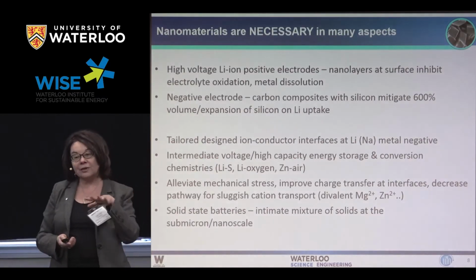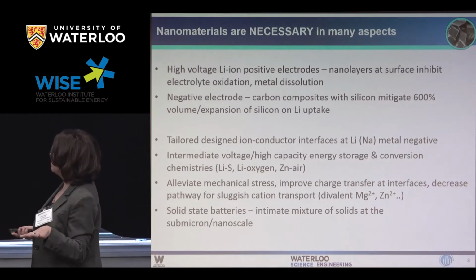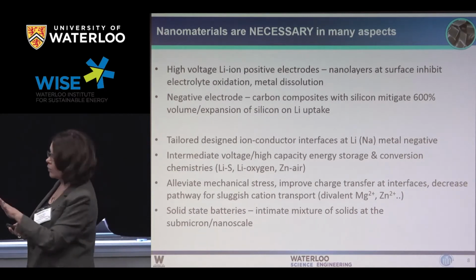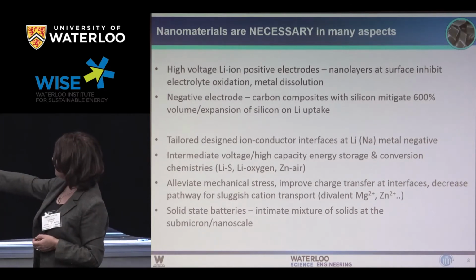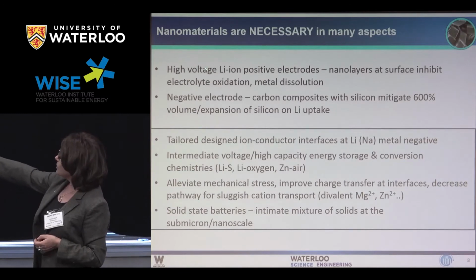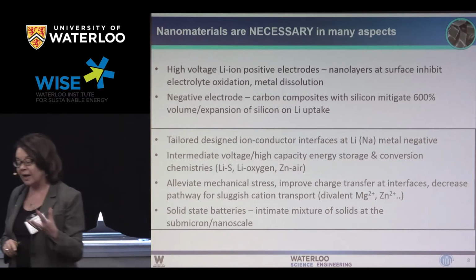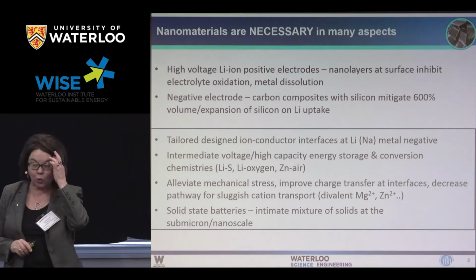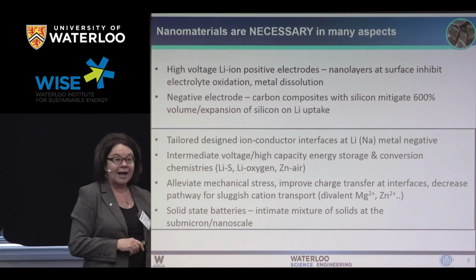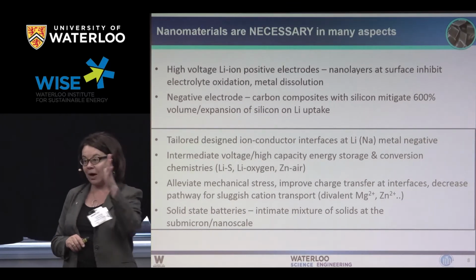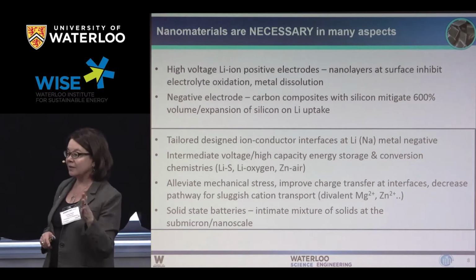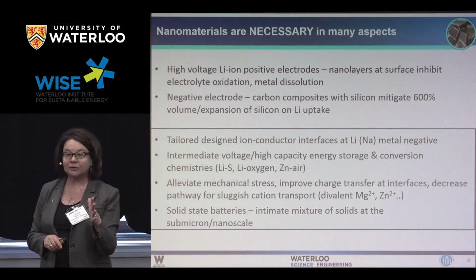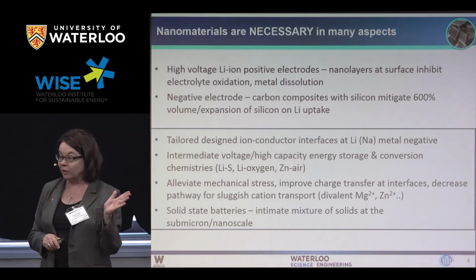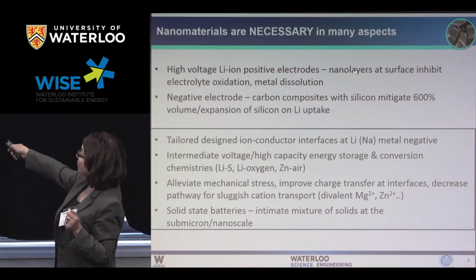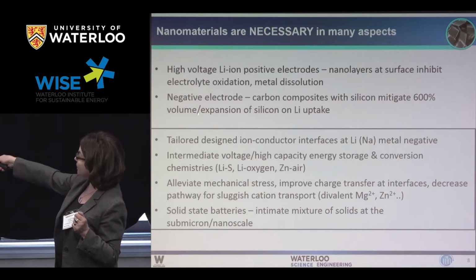So I'll tell you a little bit about where nanomaterials come into the picture. There's a lot of words here, but really I'm only going to talk about these bottom portions. So the materials in your batteries today work because there are these additives in that electrolyte that deposit on that highly oxidizing positive electrode, and they passivate that interface. And without them, it really wouldn't work at all. So we call these nanolayers at the surface, really important.